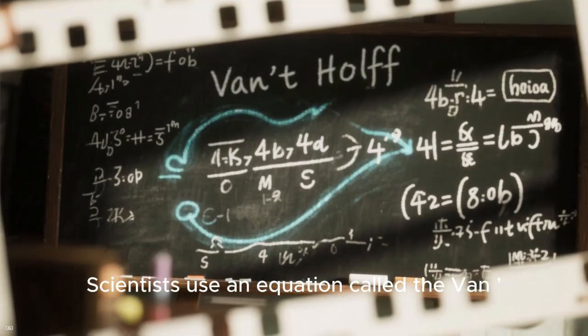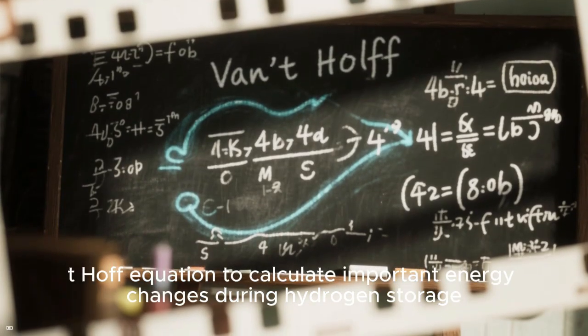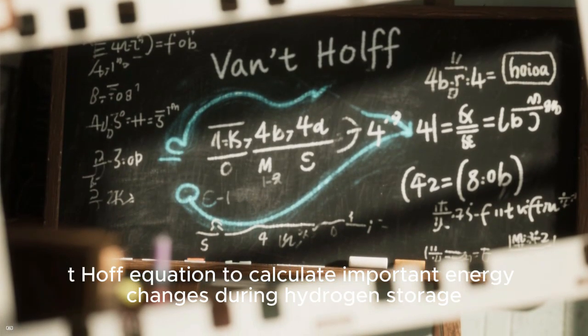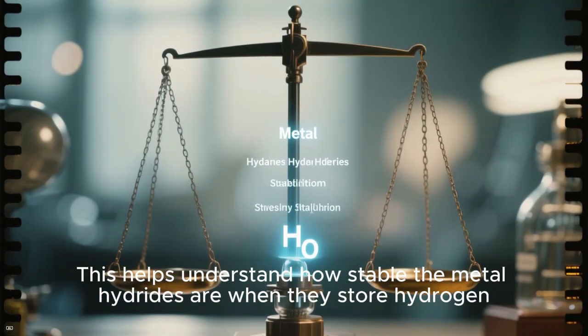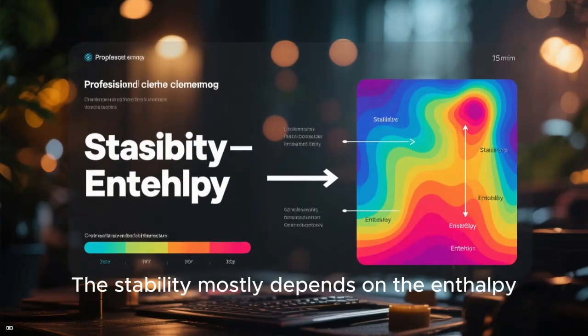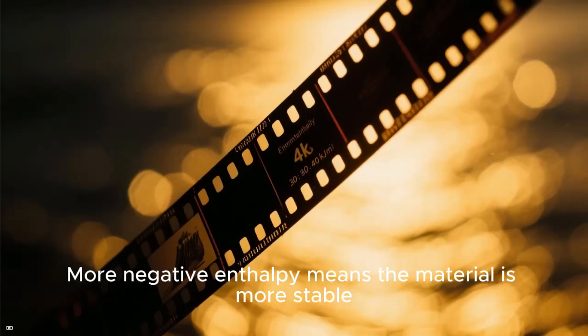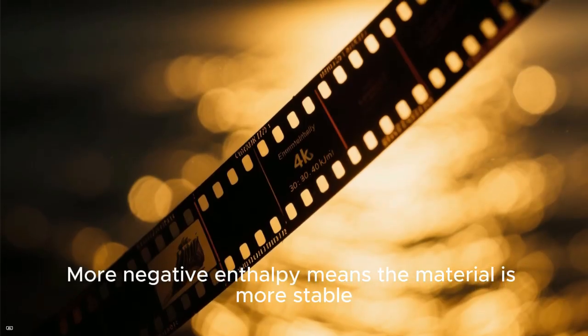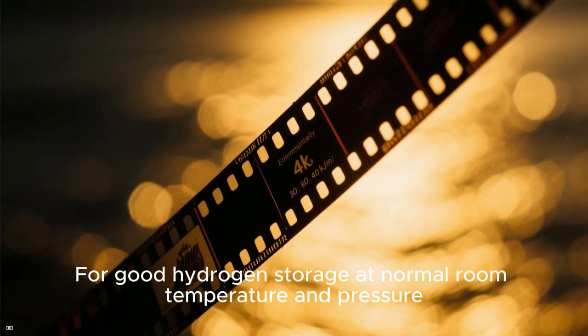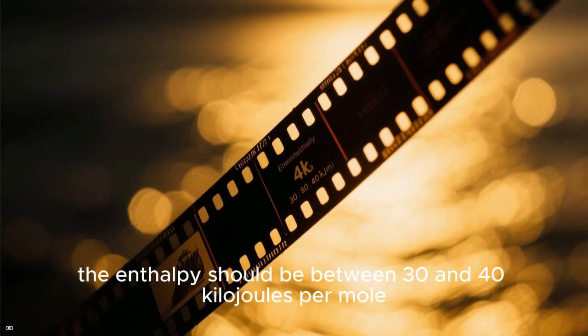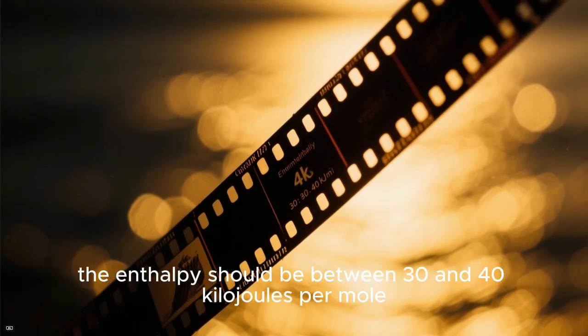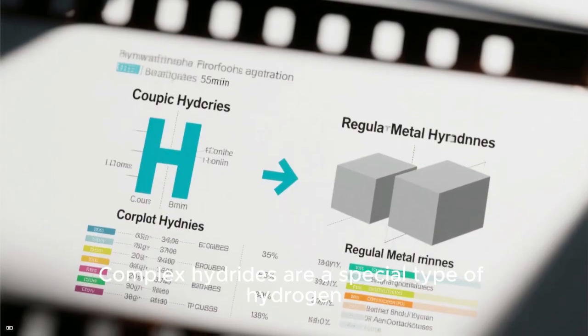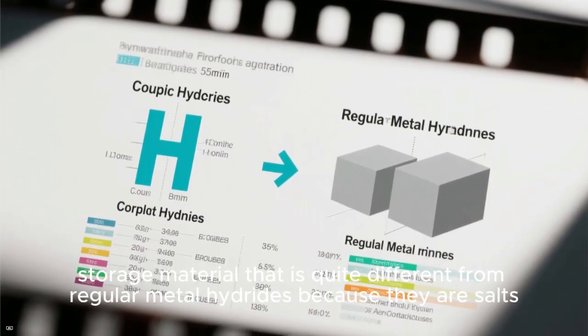Scientists use an equation called the Van 't Hoff equation to calculate important energy changes during hydrogen storage. This helps understand how stable the metal hydrides are when they store hydrogen. The stability mostly depends on the enthalpy, or heat involved in the reaction. More negative enthalpy means the material is more stable. For good hydrogen storage at normal room temperature and pressure, the enthalpy should be between 30 and 40 kilojoules per mole.